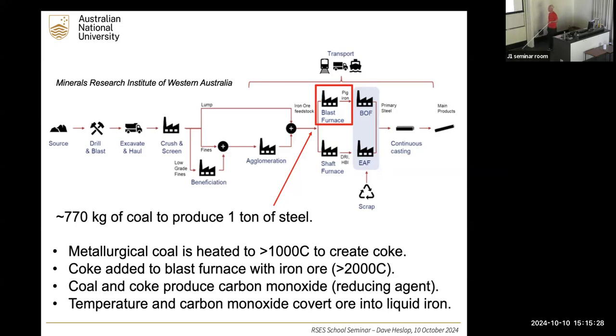And then the coke is added into the blast furnace along with the iron ore. It's heated up to around 2,000 degrees C. And that production of carbon monoxide from coking coal acts as the reducing agent. So what you get is the temperature liquefying the iron and the carbon monoxide doing the reduction, so you're outputting this liquid iron. So as you can imagine, this is pretty heavy in terms of its fossil fuel footprint.